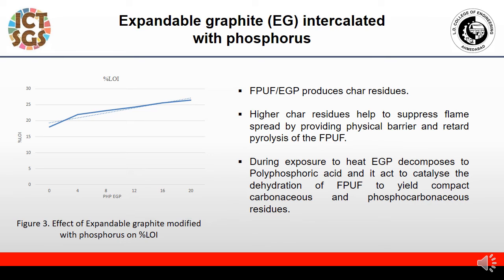During the exposure to heat, the EGP will decompose into polyphosphoric acid, and it acts to catalyze the dehydration of flexible polyurethane foam to yield the compact carbonaceous and phosphocarbonaceous residue.